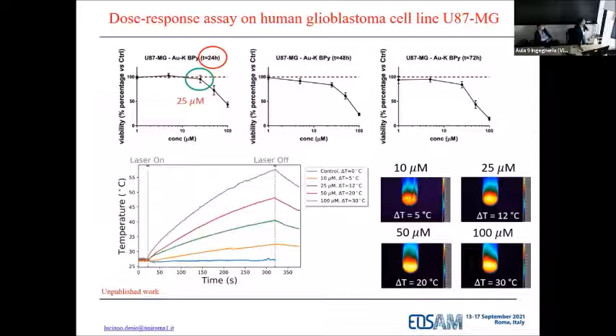Although the photothermal properties are amazing, and we are happy with that, they work with the near-infrared laser. Also, the temperature increase can be up to 30 degrees C, but there is this big limitation. We cannot increase the temperature too much. At this concentration, the temperature increase is about, let's say, 12 degrees C before washing. After washing, of course, this will be much lower.